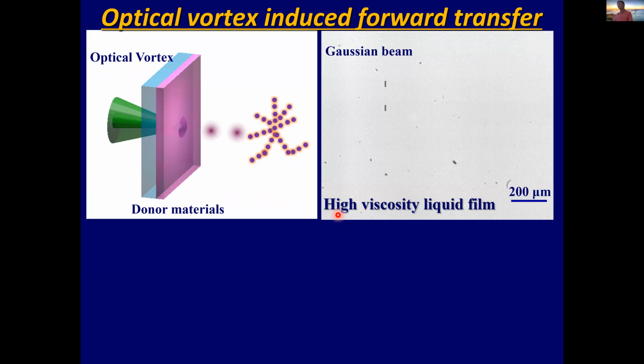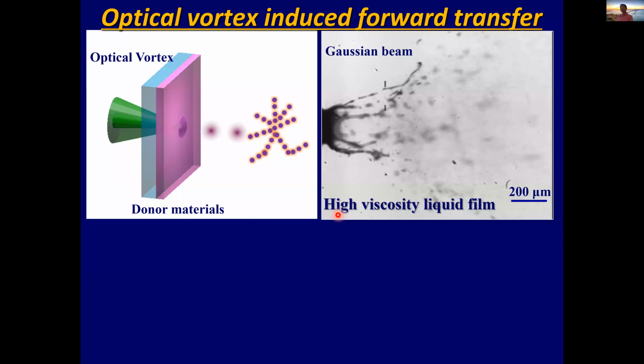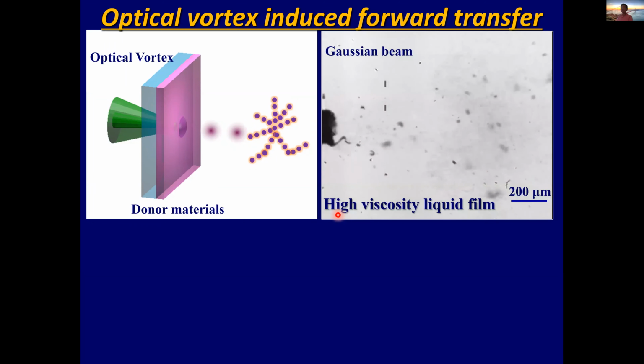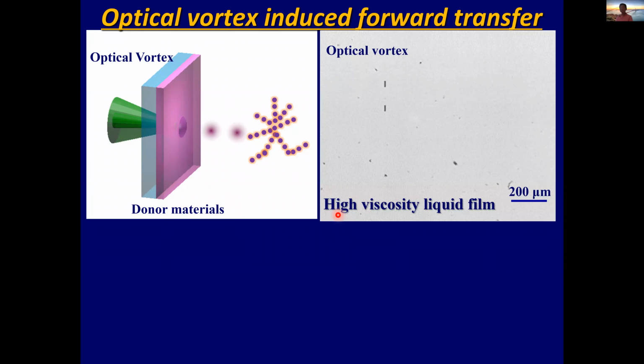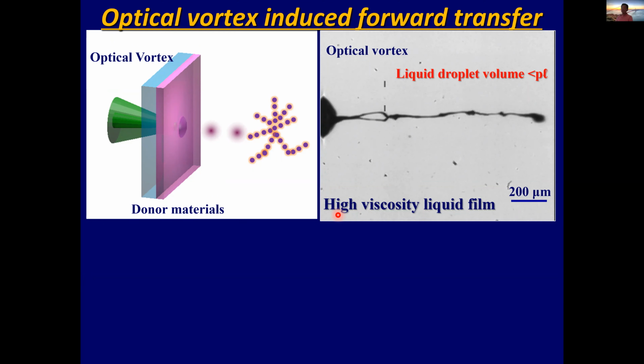The film breaks into many fragments, and the fragments fly away. We cannot control the flight of the fragments at all. Just by replacing the light source from the Gaussian to the optical vortex, namely the Laguerre-Gaussian mode, the film creates a blister home to a spinning jet. After Plateau-Rayleigh instability, this jet ejects a single droplet. The volume of the droplet is roughly at the picoliter level. This corresponds to the limitation of conventional inkjet printing technology.